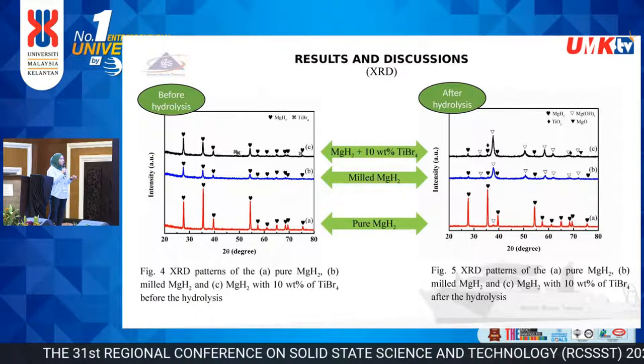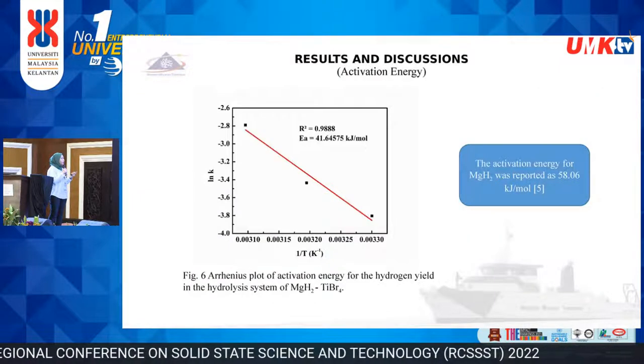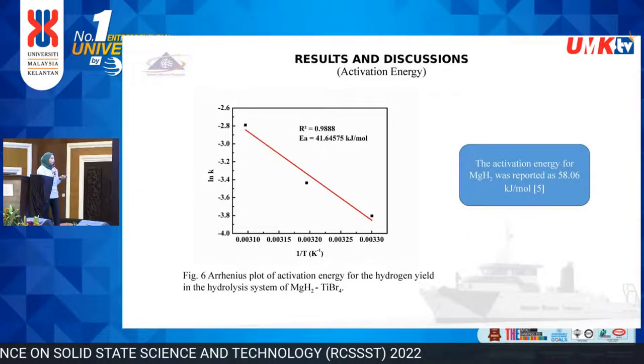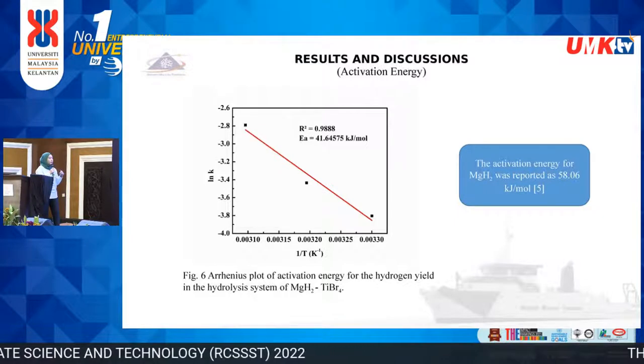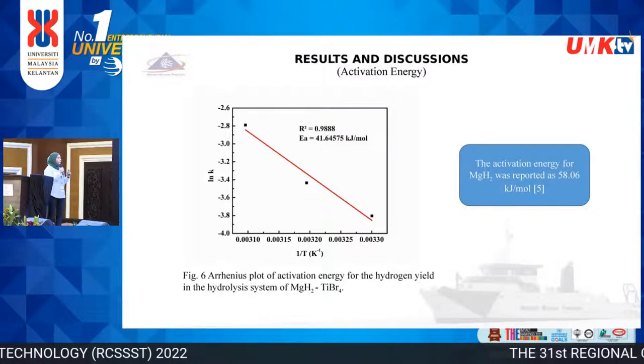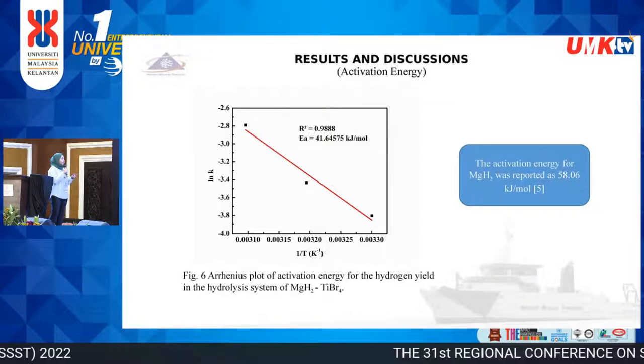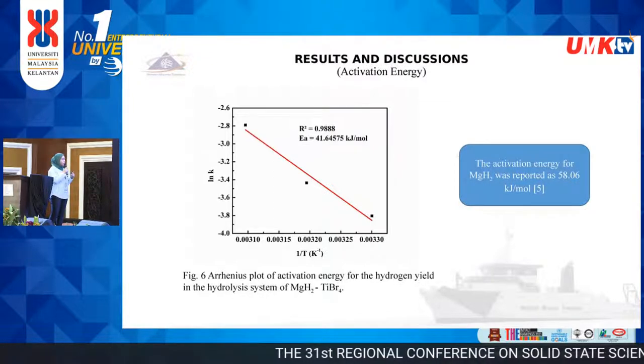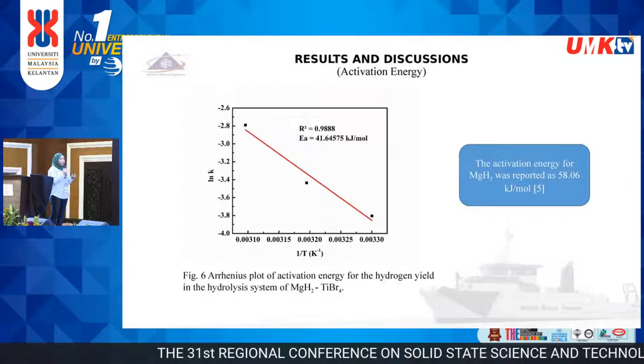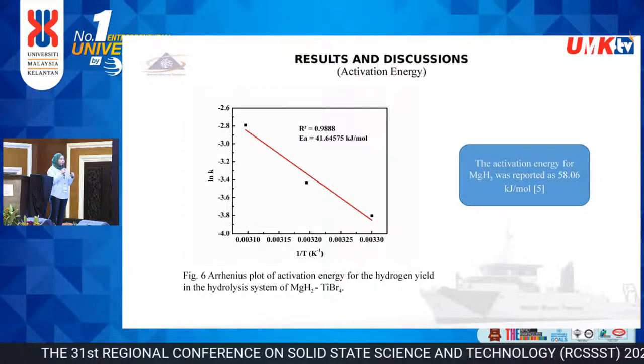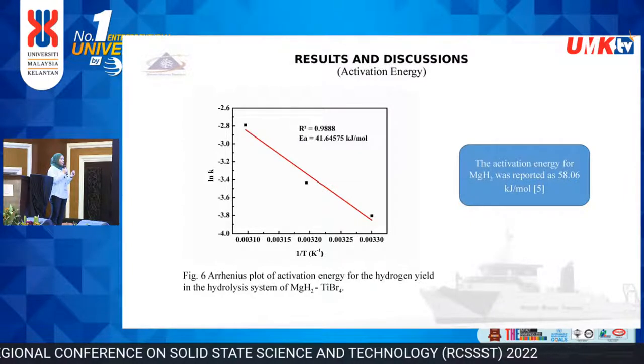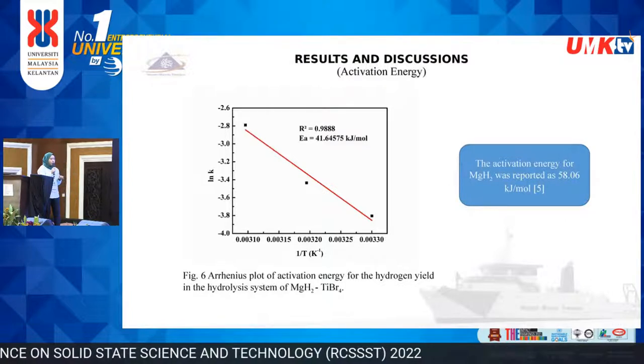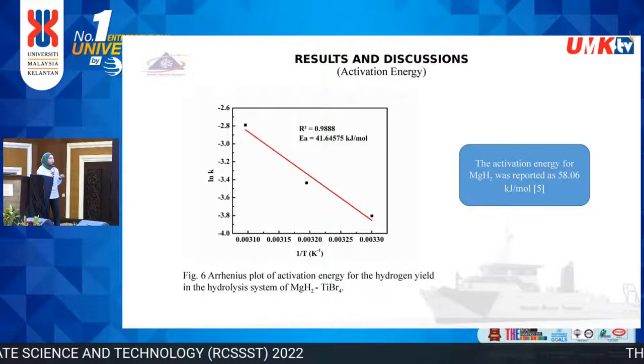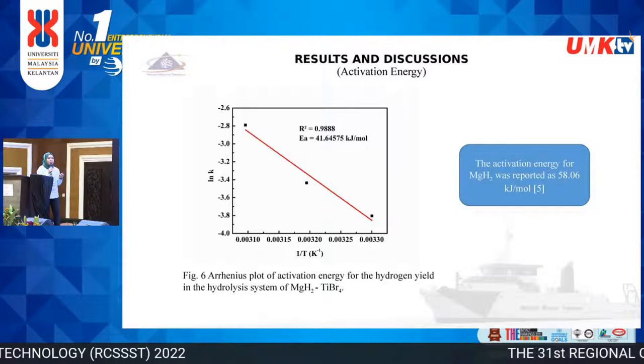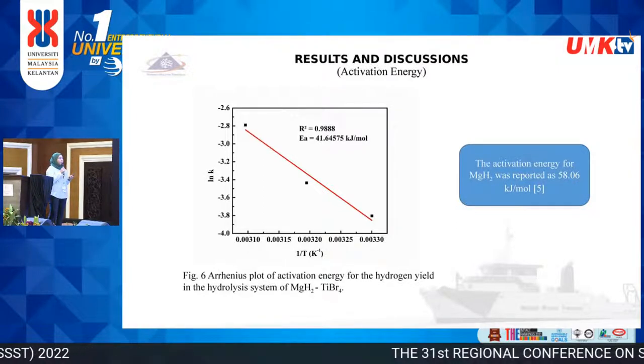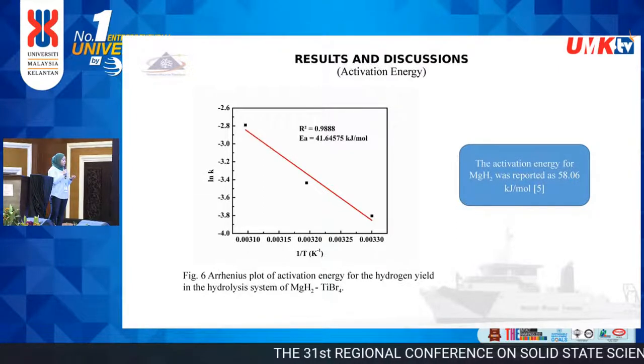So for the activation energy, this is the Arrhenius plot for the hydrogen yield for the hydrolysis system of magnesium hydride with 10% of titanium bromide. The activation energy calculated was 41.65 kilojoule per mole. When we compare with the activation energy for magnesium hydride, it was reported as 58.06 kilojoule per mole. So for this, we have successfully reduced the activation energy.